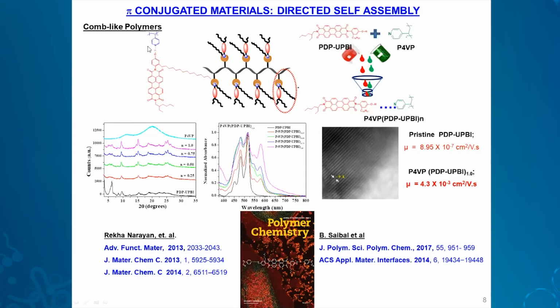perylene bisimide and self-assembled it with a polymer. This is a poly 4-vinyl pyridine. So schematically it would look like this. If this is the polymer backbone, we are assembling these n-type material along this polymer backbone. So the polymer brings in the mechanical stability and flexibility, and the small molecule brings in the charge transportability. So the way it is done is we just mix them together in solution and evaporate the solvent, and then the system acts as a single unit.